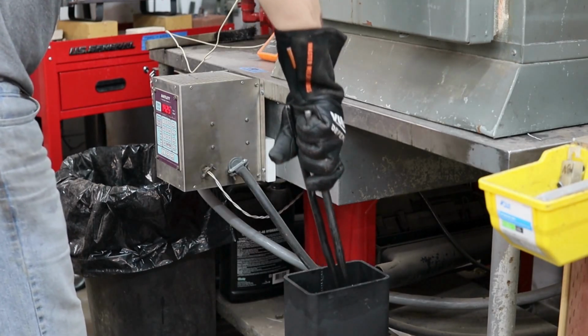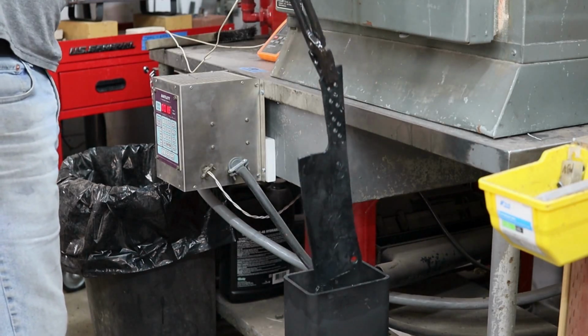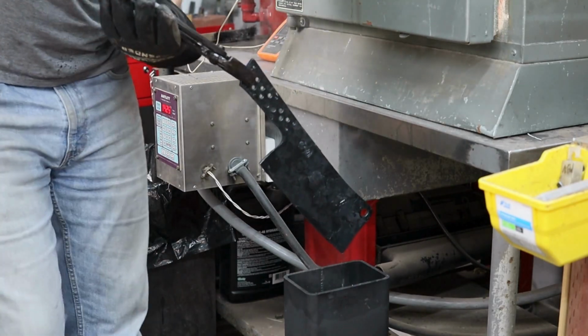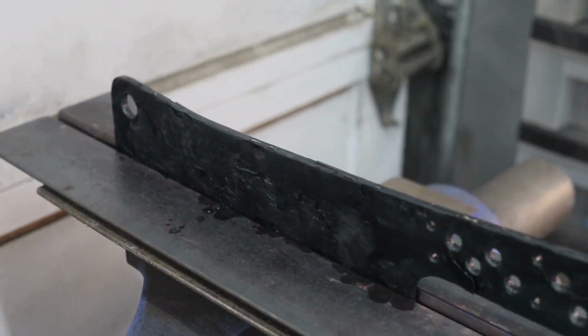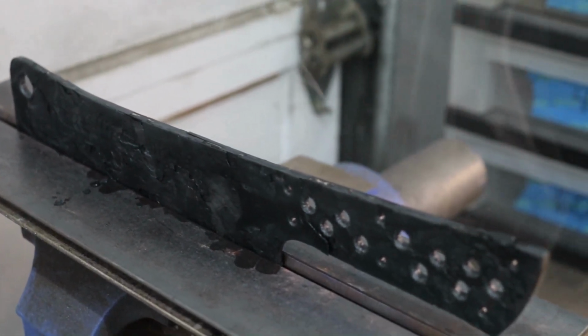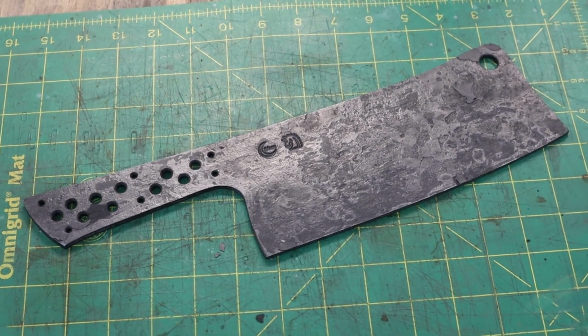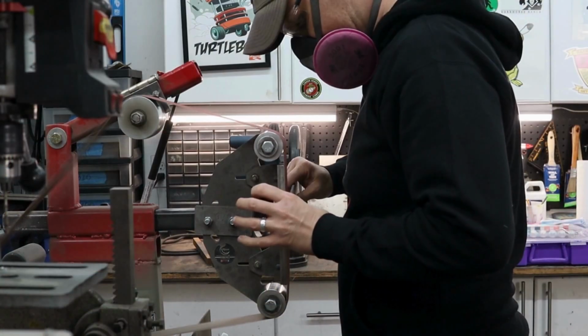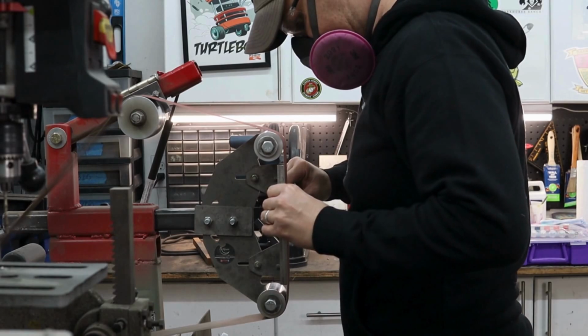Somehow there don't seem to be any cracks anywhere. I'm not really sure what exactly I heard during the quench, but there don't appear to be any problems with this blade. I let the knife cool to room temperature in a vise to make sure that it hardens perfectly straight. I tempered the blade for two 2-hour cycles at 425 degrees Fahrenheit. That should give me a hardness of around 60 Rockwell.